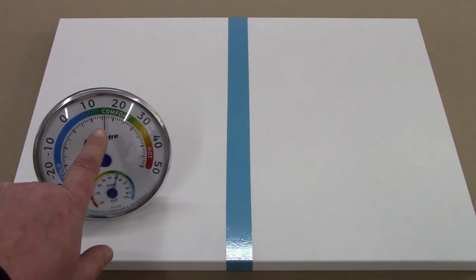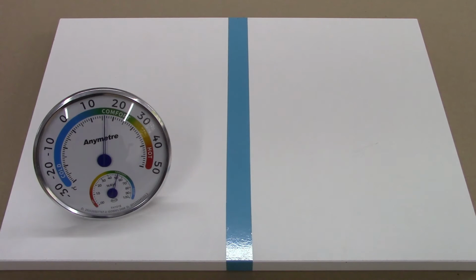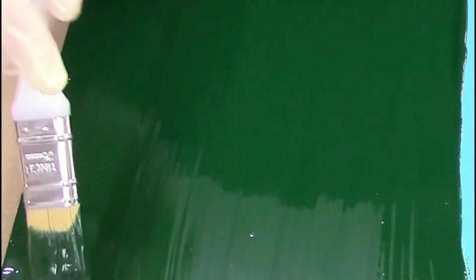So let's recap on what you should do to avoid this issue with gel coating. 1. Ensure a good working temperature and condition the mould and products to 15 to 20 degrees C. Definitely avoid laminating in colder temperatures when GRP moulding. 2. Ensure a good thickness of gel coat and avoid applying it too thinly.